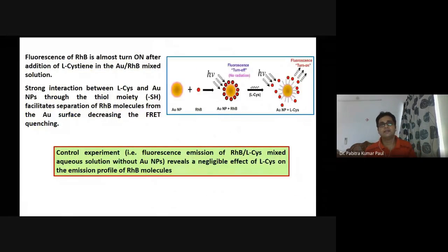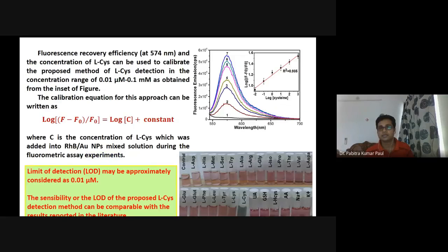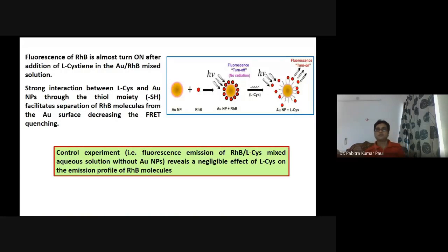This is the schematic protocol presentation of the recovery of the fluorescence, because the energy transfer is modulated when we apply the L-Cysteine. This modulation and change of the energy transfer is basically linear. That's why you see this curve. This curve is linear against the log concentration. So that's why we can say it is a very good platform for sensing the amino acid.